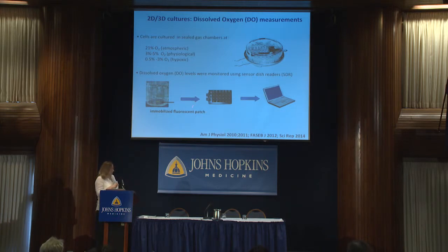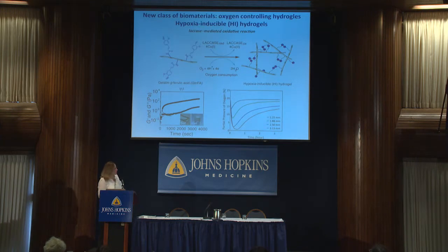We developed, and I won't show you that, microfluidic systems that can control the level of oxygen that the cells actually see in their very close microenvironment. But because we are interested in three-dimensional, we said, maybe we can develop a hydrogel that can mimic this hypoxic condition. For that, we apply a specific reaction through laccase enzyme that consumes oxygen. We managed to generate hydrogels that form while generating hypoxic conditions.